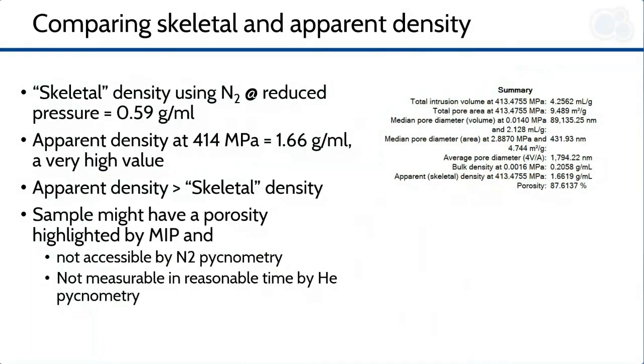The so-called skeletal density using nitrogen at reduced pressure was 0.59 grams per milliliter. We are not considering the density measured by helium because of the slow diffusion in the granules structure and never reaching the pressure equilibrium in a reasonable time at room temperature. The apparent density measured by mercury porosimetry at 414 megapascal is 1.66 grams per milliliter, a very high value, almost triple the density measured by nitrogen. This indicates that the sample might have an inaccessible porosity, slowly permeable by helium, but not by nitrogen at reduced pressure. Mercury at high pressure collapsed the structure, thus measuring what was before a closed porosity.